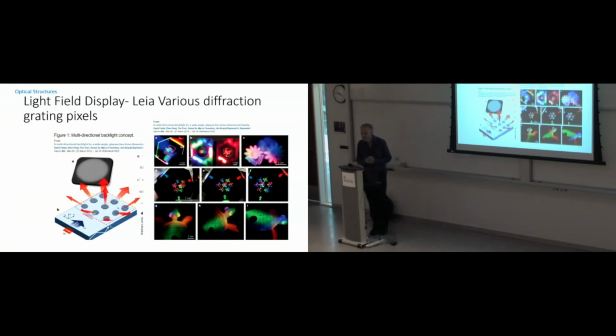Yeah. So you have shown an image of the high aspect ratio features, like in that process, right? I believe that's made in PDMS. Well, it was made in SiO2 and silicon, and then we just cast it. Do you experience any collapsing of the high aspect ratio features of PDMS, collapsing with each other due to surface energy? What we have observed is if it's too floppy of a structure, they can kind of come together, and then you get stiction together. Although one group at HP Labs turned that into sort of a feature.